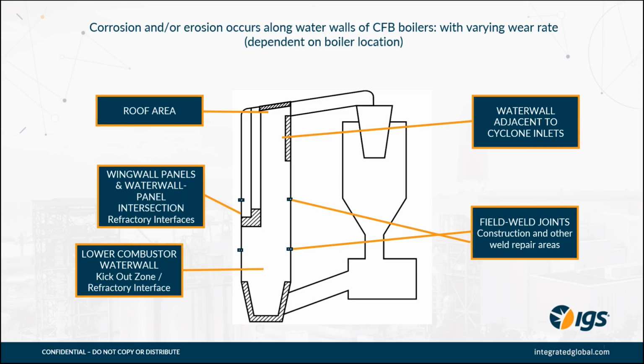Where wing wall panels or evaporator panels penetrate the front wall, most commonly of the boiler, there is a sudden step change in direction of the ash flow as it's sliding down the tubes and reaches an impact point. This is a known site of localized erosion, and obviously another great point for high velocity thermal spray cladding to address that localized erosion. Adjacent to the cyclones, the roof area, and the front wall, the erosion phenomena changes to more of an impact erosion rather than a sliding ash erosion that occurs in the lower combustor.